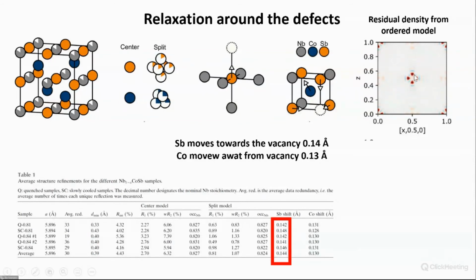Okay, I just put in an extra antimony site and have a disorder in my antimony. That's all very fine, and I can refine how far the antimony moves away, and it is about 0.14 angstroms. I can see the exact same thing if I do the 3D delta PDF. Then if I have a niobium atom, there's a negative, so there tends not to be an antimony. Or conversely, if there's a vacancy here in the middle, then antimony will move towards the vacancy. So all is very good.